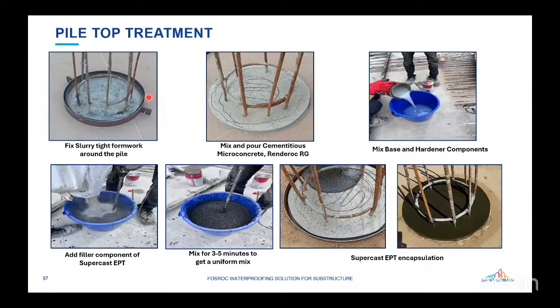So here you can see how the pile head treatment is done. So this is the waterproofing layer, and this is the pile head. The broken pile head has to be reprofiled using a micro concrete. Once the reprofiling is done, this will be the finish. After the reprofiling, there is a second layer of waterproof epoxy grout which will be applied onto the top surface and onto the side.